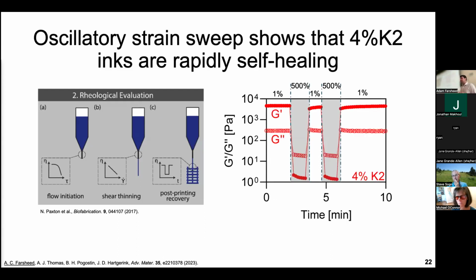And the third property that I would argue is maybe the most important property is that our material is what we call rapidly self-healing. And so in this test here, what I'm showing is an oscillatory strain sweep, which basically in these white regions is applying a very low strain. And then in the gray regions, I'm applying a bunch of strain. And so as we shift from the white to the gray region, we'll notice that the red lines will invert. And so what we're seeing is basically the liquefaction of our sample as we apply that super high strain. But the most important point is actually that interface between the gray and the white regions, where we're able to see within a matter of seconds, our material is able to recover all of those gel-like properties.